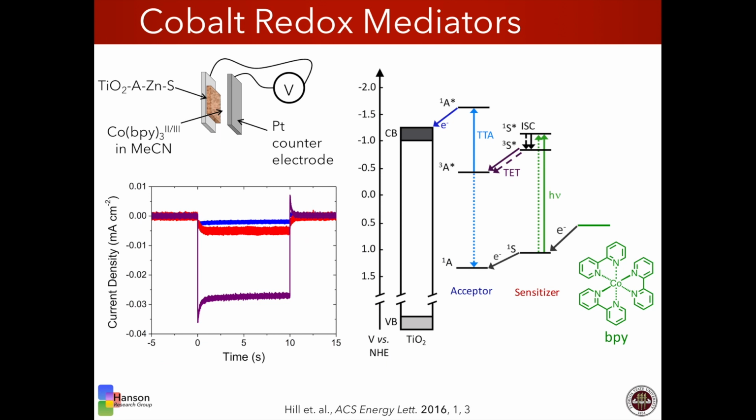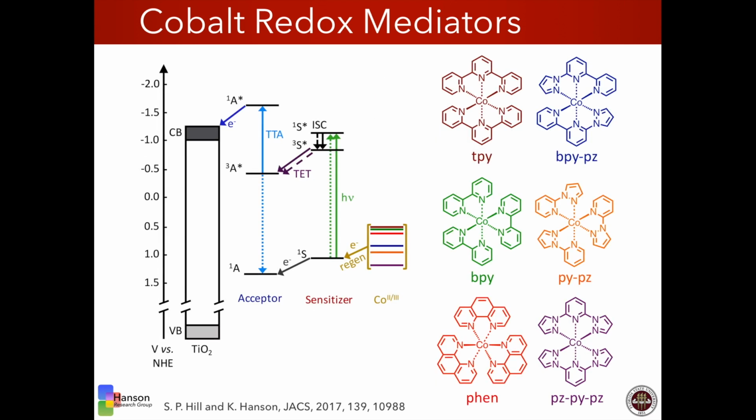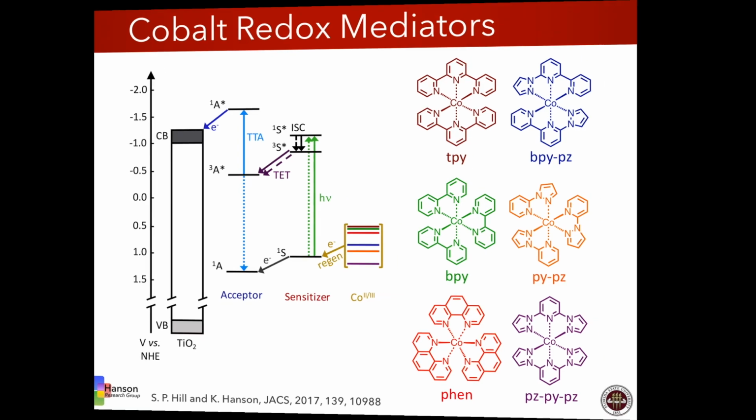To achieve sustained photocurrent in the device, we used a cobalt-based tris-bipyridine redox mediator. In this article, we chose to explore the effect that the redox mediator has inside of the solar cell on the upconversion process by incorporating 6 different cobalt-based redox mediators, all with similar size and varied redox potential in order to probe the events in the system.